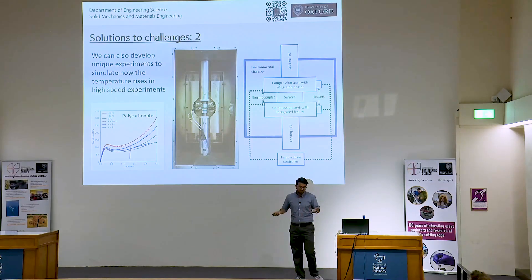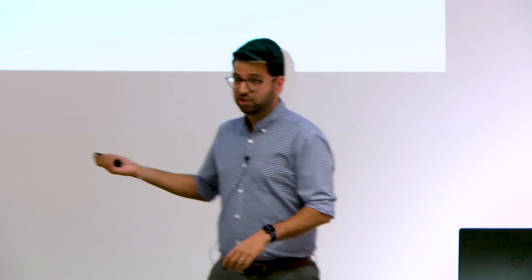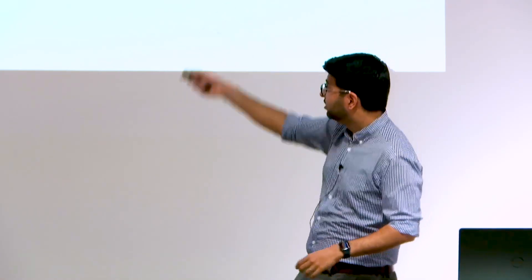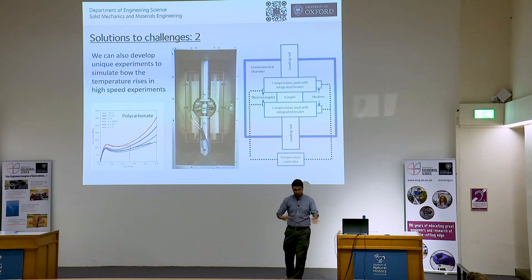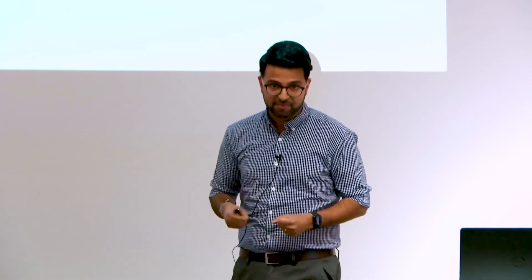At the top are experiments in tension and at the bottom is an experiment in compression. You can see a difference between the higher-speed experiment where a lot of heat is generated versus the lower-speed tension experiment where there is enough time for heat to leave the material and get dissipated into the environment. This thermal camera can go to 1000 frames per second. Another potential solution is to create new experiments using an oven that can decrease or increase temperature — decreasing the temperature to recreate the response the material sees when impacted at high speed, and basically simulate the temperature rises at a slower speed using tools not available at high speed.